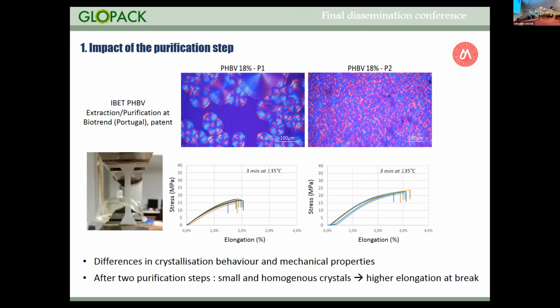That means that you elongate the materials until the break. You can see, if you record the stress as a function of the elongation, that after a second cycle of purification, you increase all the mechanical parameters of the materials, so both the stress at break and also the elongation at break. So we try to understand why we had such difference, why the microstructure was so impacted by a